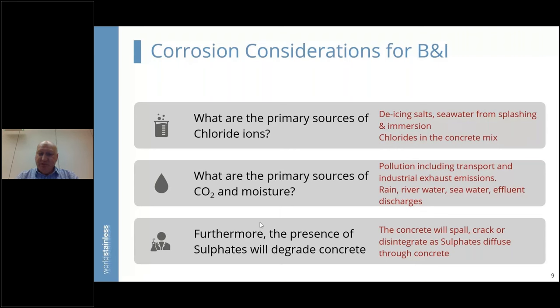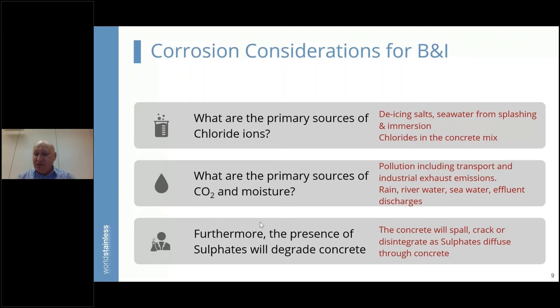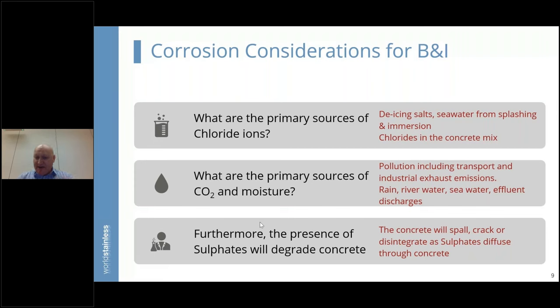The moisture and CO2 come from pollution in the area — including transport and industrial exhaust emissions — and moisture from rain, river water, seawater, and effluent discharges. When these two things diffuse through the concrete, they effectively create carbonic acid, turning the alkaline nature of concrete acidic. We must also never ignore the presence of sulfates: if concrete structures are exposed to sulfates, the concrete degrades quickly, cracks, and small pieces fall off as the sulfates diffuse through — speeding up the overall corrosion process.